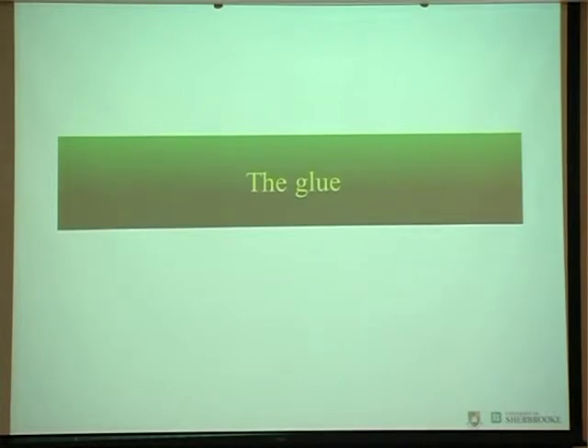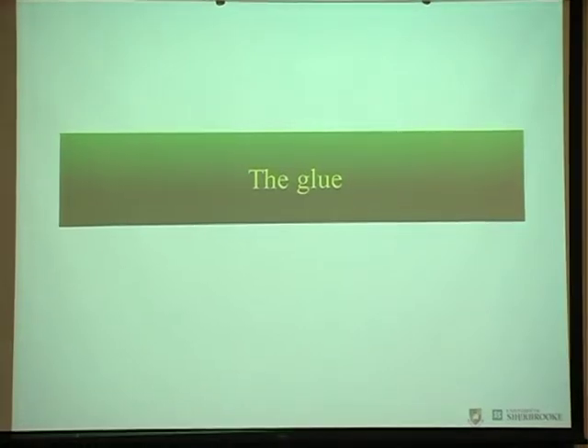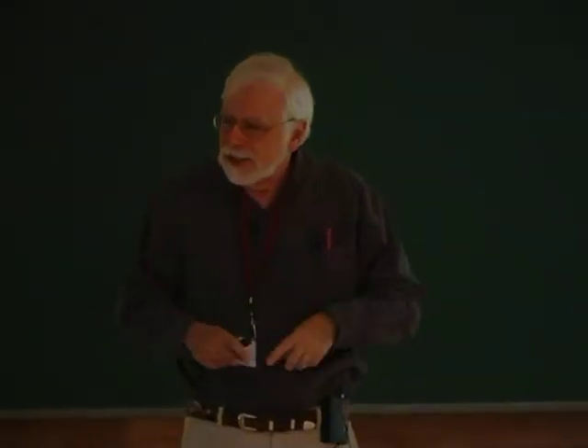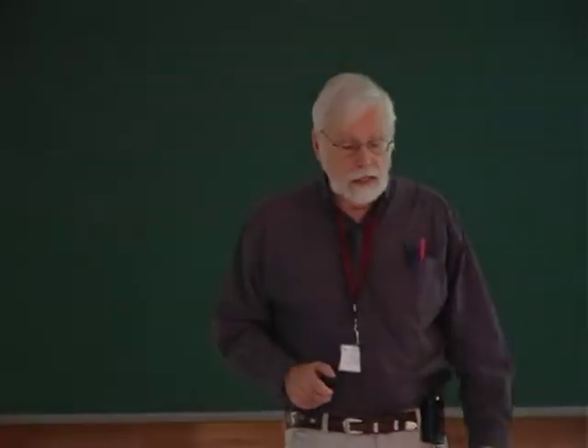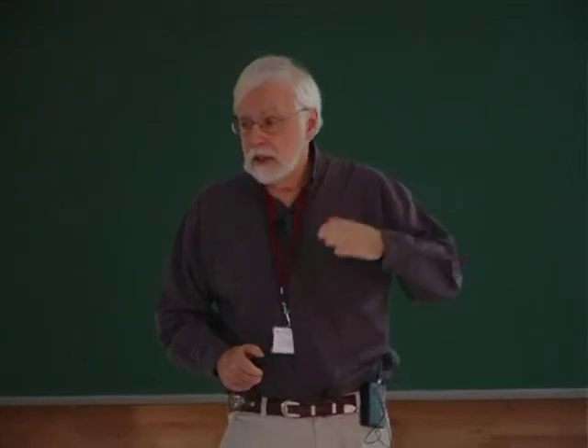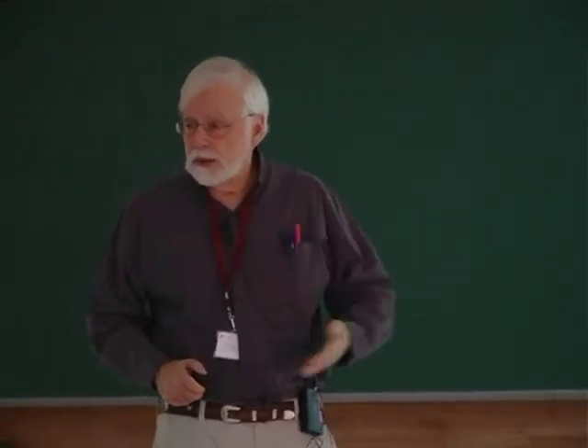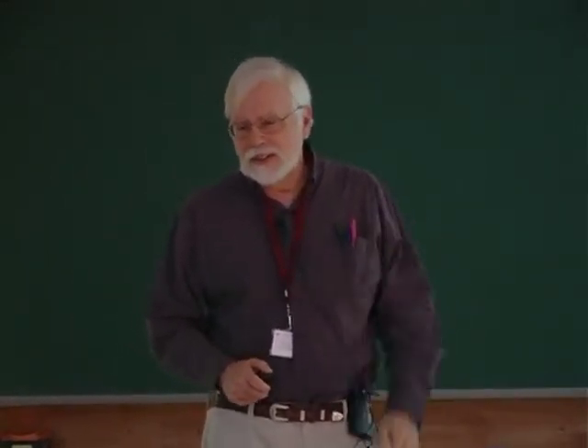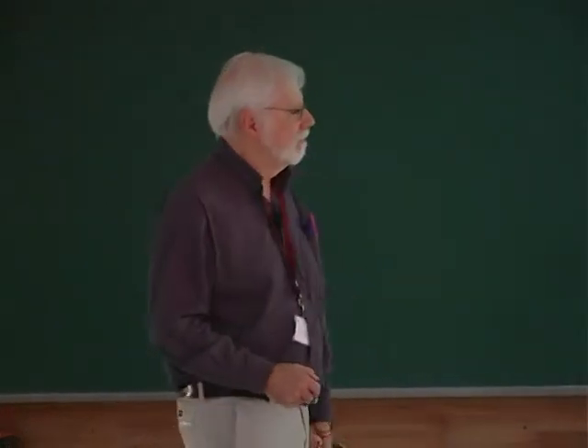So the bath has some broken symmetry. Yeah. And it is self-consistently checked with the cluster that you're keeping? Exactly. I mean, the cluster does not have any broken symmetry, but in the calculation you solve this cluster and in the bath you put anomalous averages, and then in the DMFT cluster self-consistent solution, you see whether this gap survives or not.